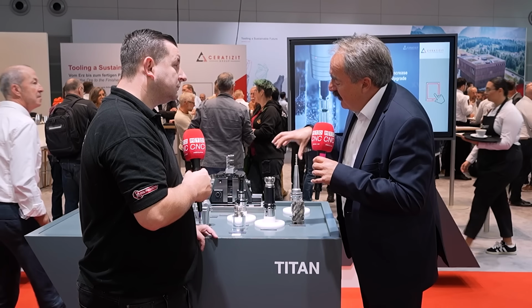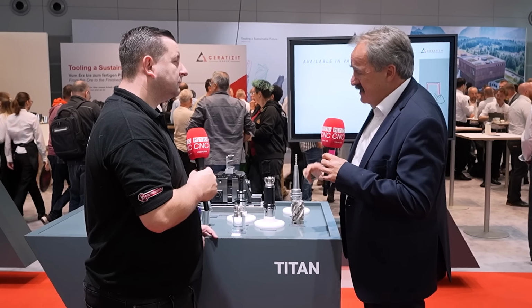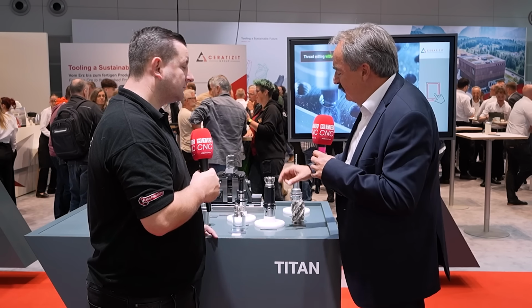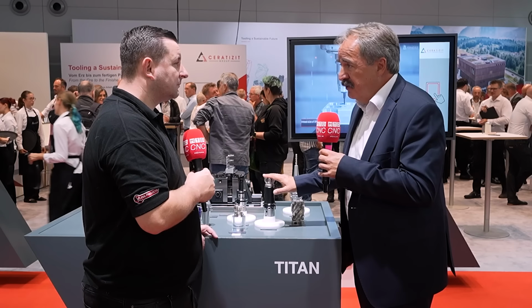What I'd like to draw your attention to is that we developed quite a while ago a specific coating for titanium machining, and it's still unique on the market. It's a CVD titanium diboride coating, which gives you very specific behavior during the application. It's very, very smooth. Because of the crystal size, it's in the 50 nanometer range, so it creates a lot less friction, which means less temperature, and it has a very high chemical stability and a high hardness. In combination with a high compressive strength in the coating, which gives you an incredible edge stability. So with that tool, you are very reliable, and you can increase your material removal rate even further on titanium with these tools and with this grade.